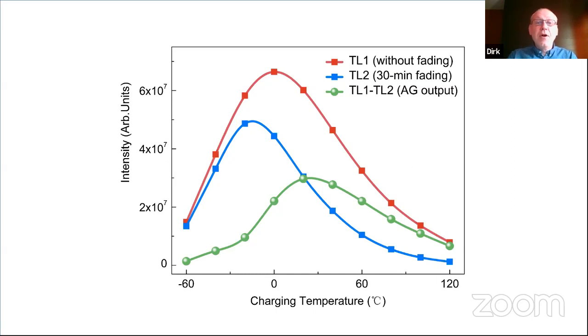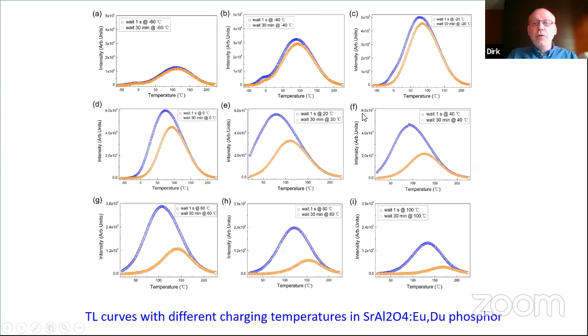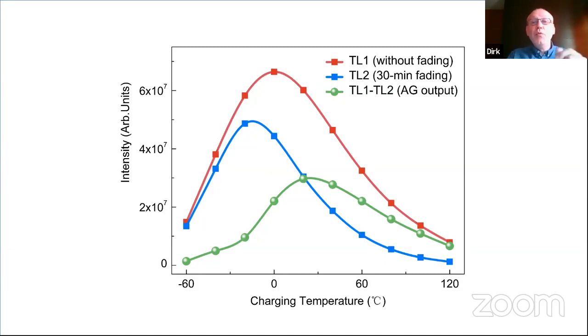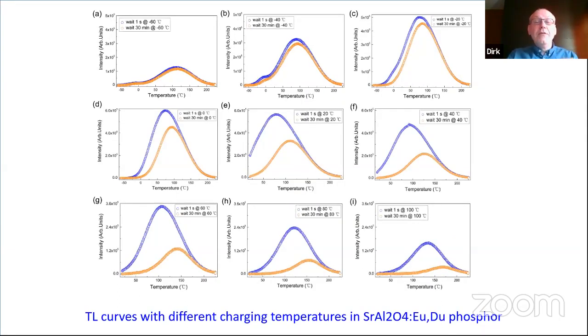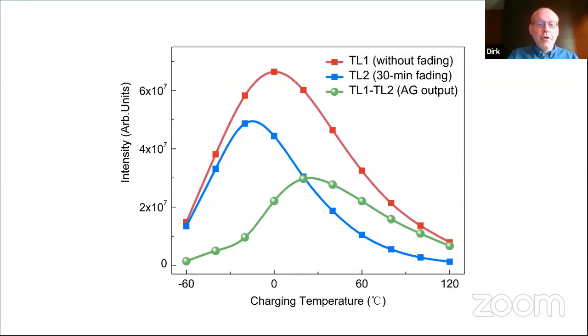It's an even more complicated graph, because in red, we have the total thermoluminescence intensity as a function of temperature without fading, so without waiting. So it's the total area of the curves in blue. And on the next slide, here in blue, we see the total intensity of the TL curves, here shown in orange. So the colors are not perfectly chosen, apologies. And the difference between these two curves gives us how much light is emitted during half an hour by persistent luminescence as a function of temperature.